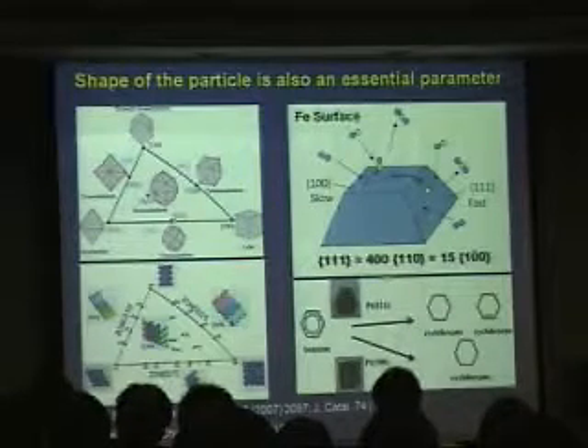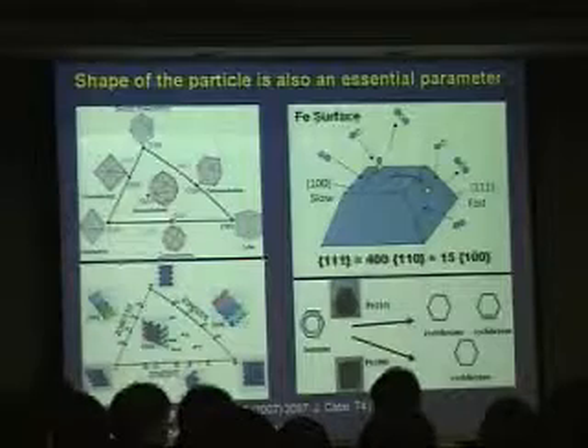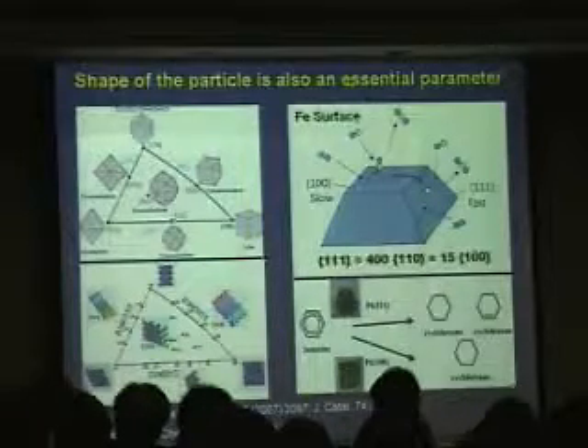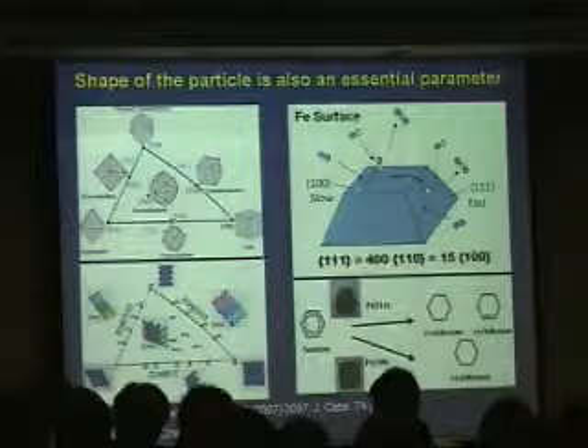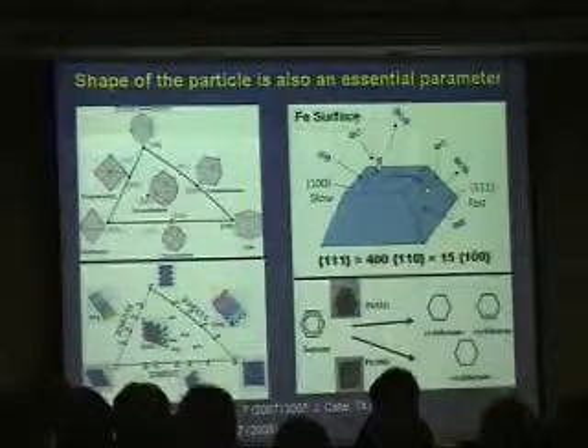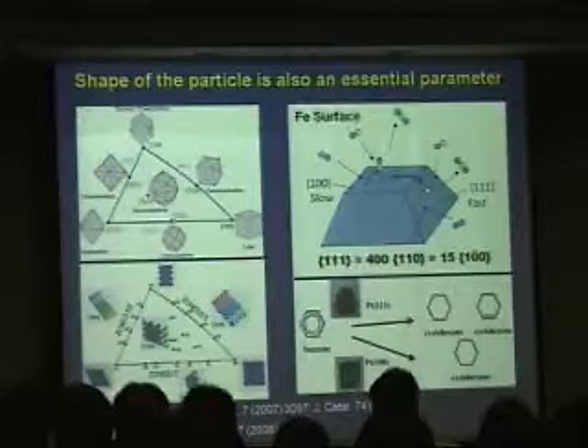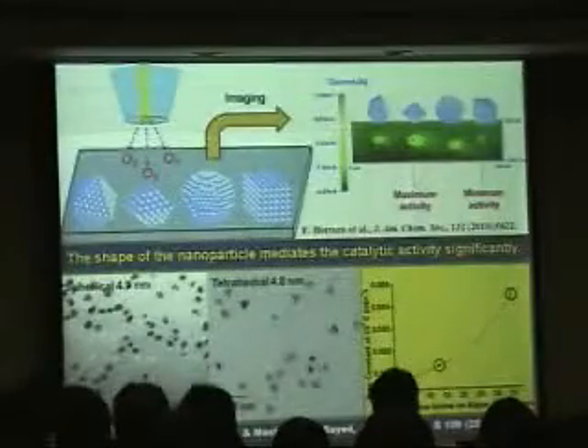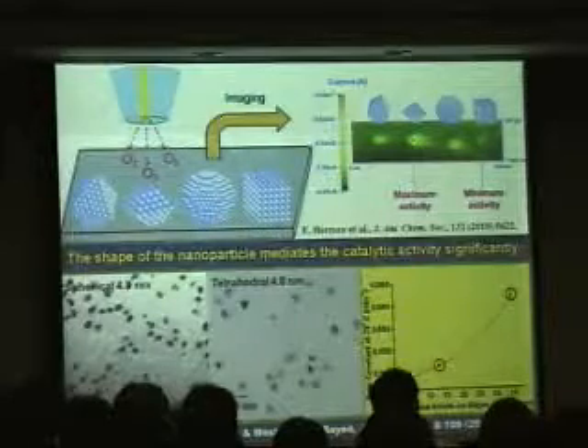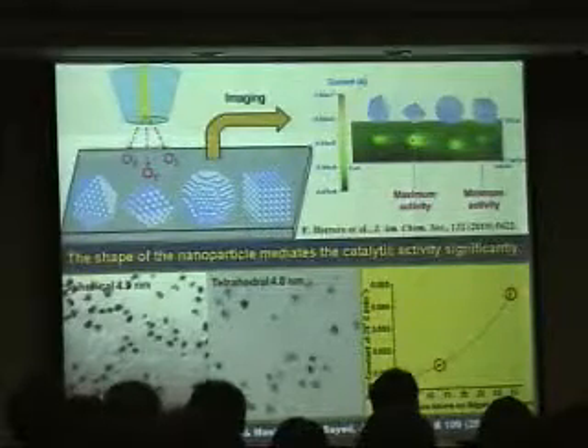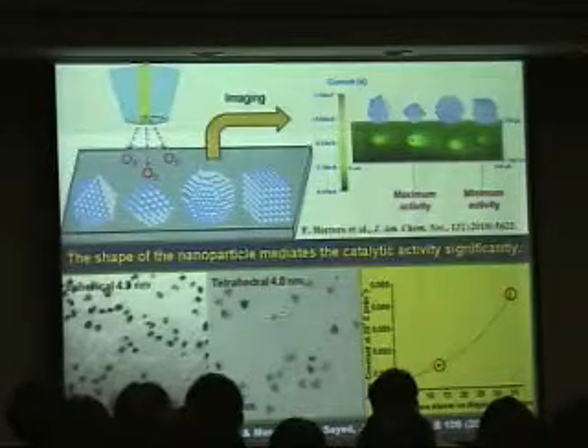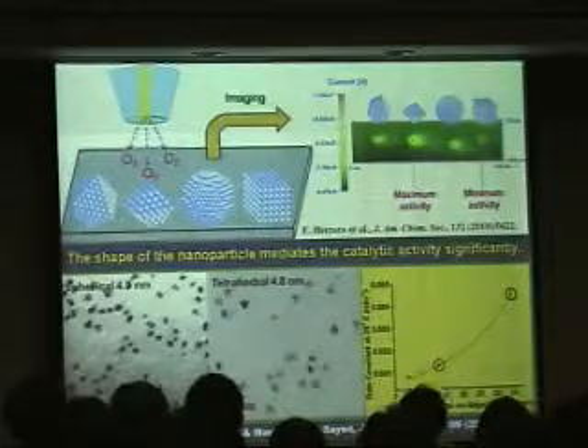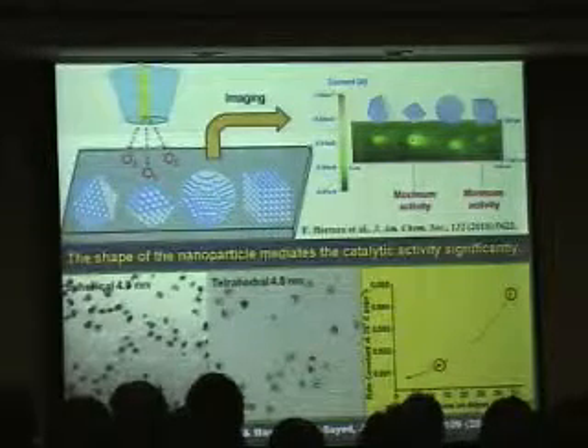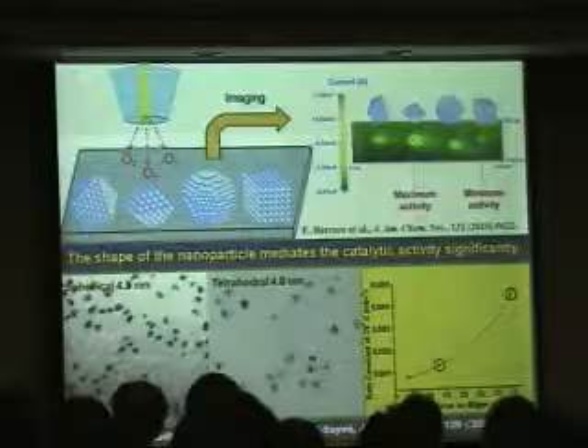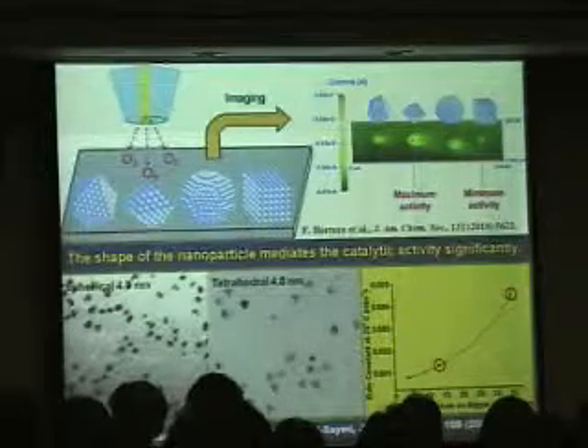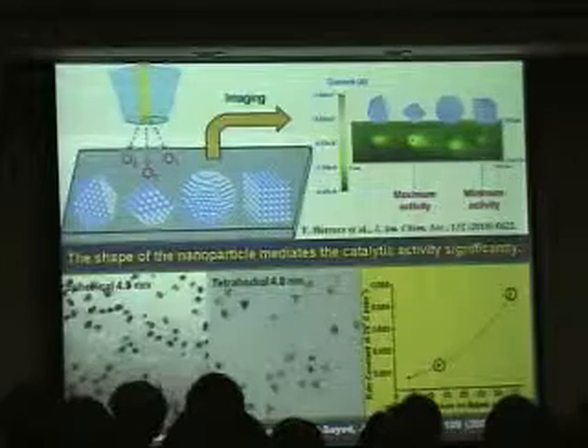For example, this is a typical old story: the coordination of the atoms on the surface not only influences the activity, but we can also detect that it influences the selectivity of the reactions. From practical reactions, there are also some good examples for metal particles, especially noble metal particles. This is a typical example from work on platinum nanoparticles. Even if they keep the same size, 5 nanometers, the reaction rate is rather different because the shape of the particle is changed at such a small nanoscale.